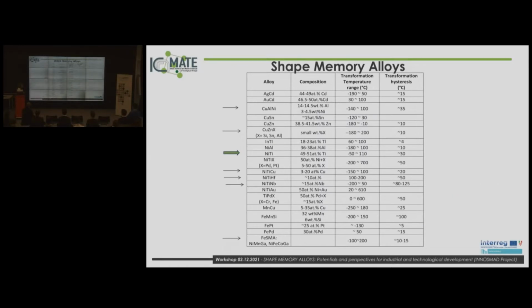Which kind of alloy can we use for shape memory? A very different kind of alloys. We can consider two principal families of shape memory alloys: the copper-based shape memory alloys and the nickel-titanium-based shape memory alloys. The copper-based is interesting, particularly for high temperature applications. In this table you can see the transformation temperature and the possibility to use this material in a particular range of temperature. The transformation hysteresis is the parameter useful for the application, and the principal materials which can express interesting, reliable and important properties for application are the copper-based, and the principal is the nickel-titanium system.